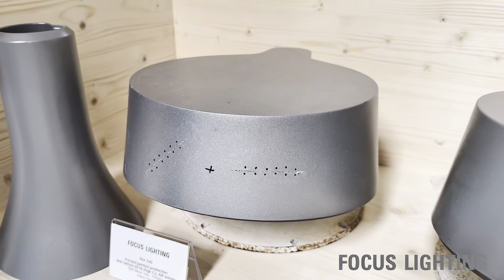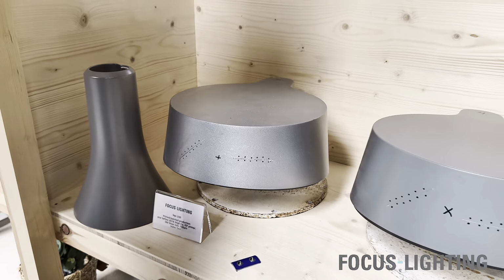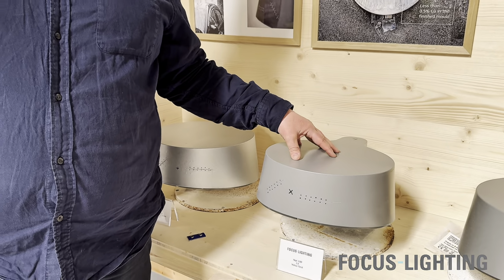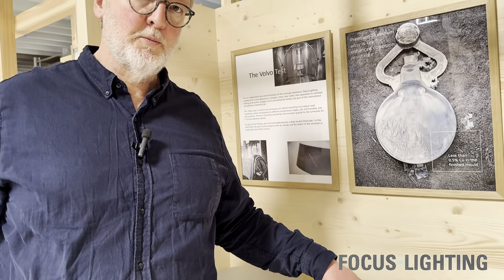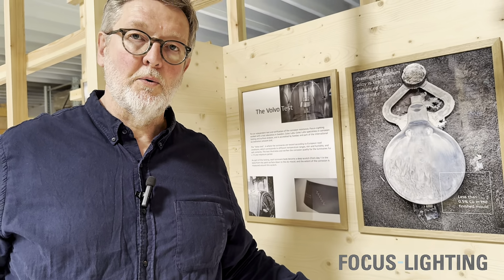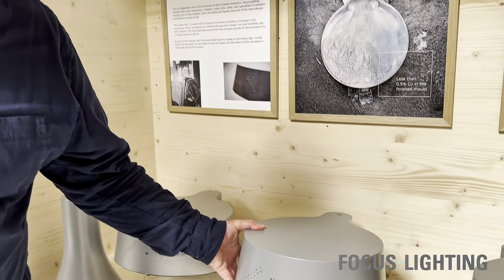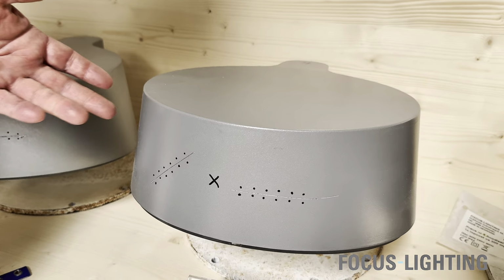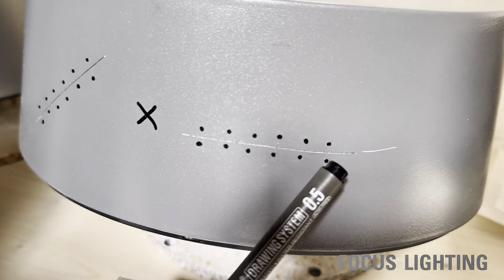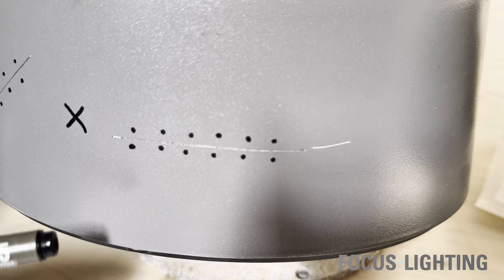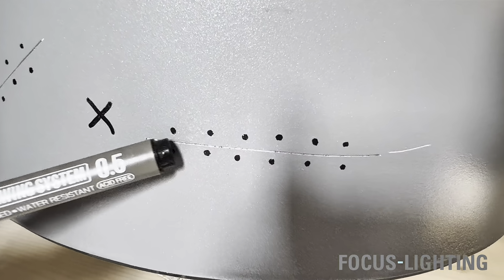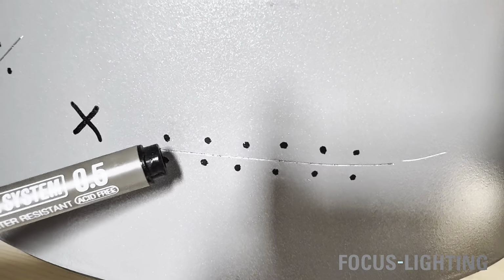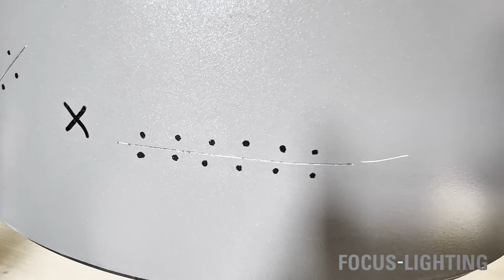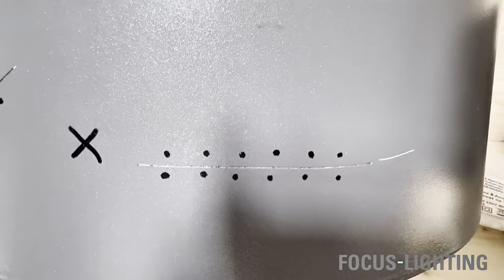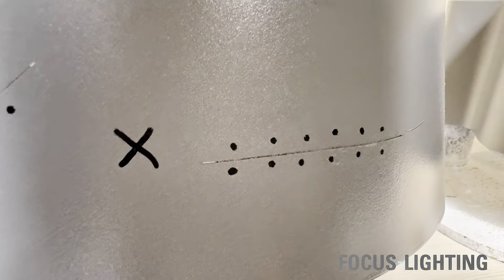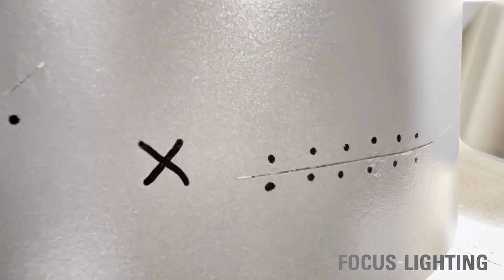So what we did over the years is that we have improved the aluminum mold, the aluminum quality, the primer, and the top coat. And here you would see what we call the C4 standard surface. Again, they have made a scratch, and after 10 years, you can see there's actually a little bit of blistering around this scratch here, which is the first step of the paint going off. But it's far better than what we had on the previous luminaire.